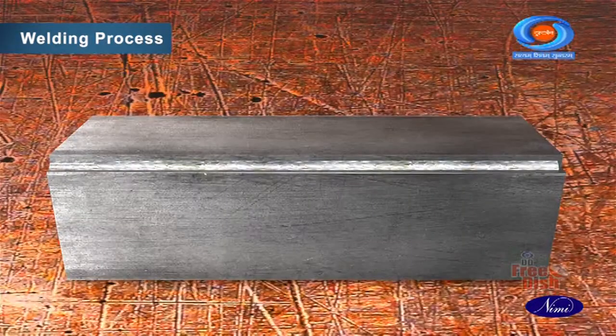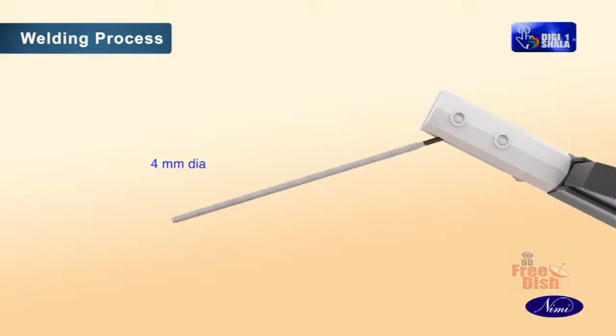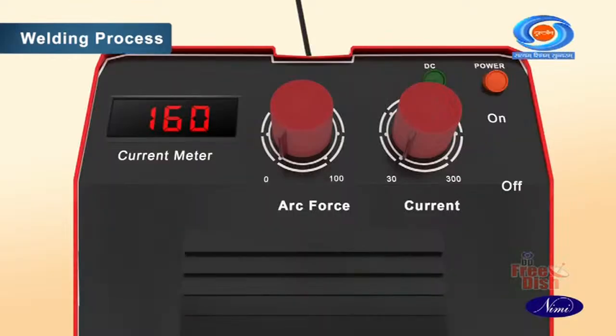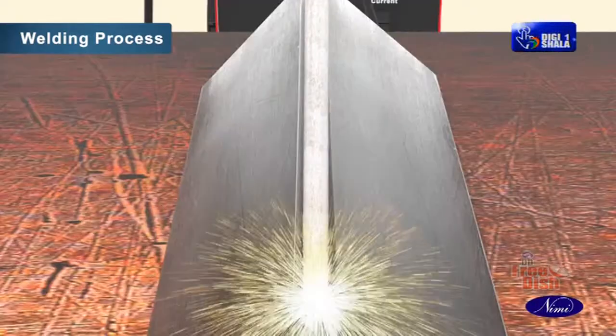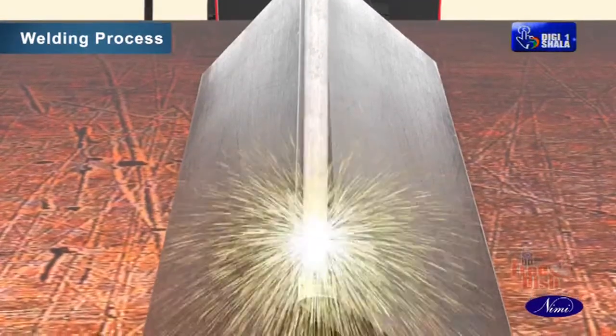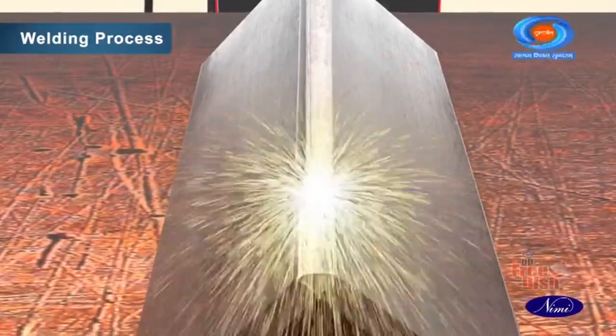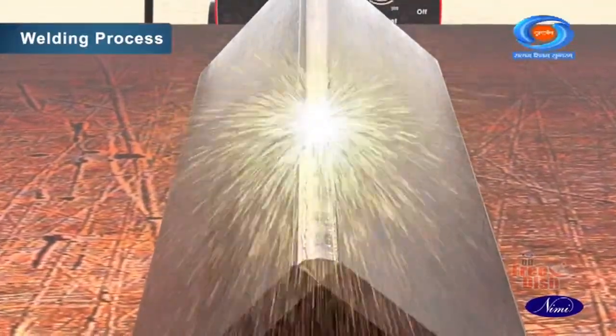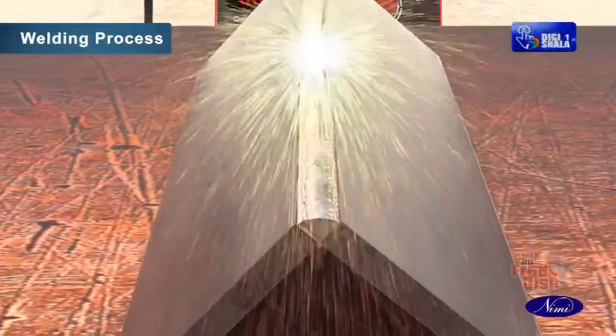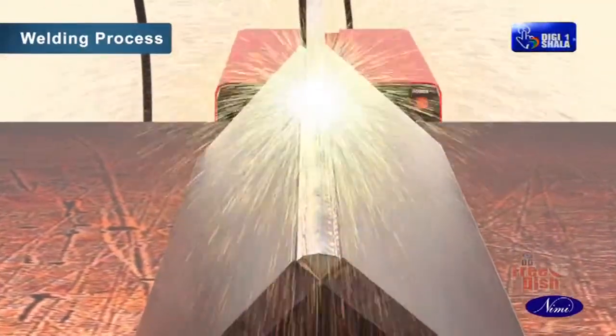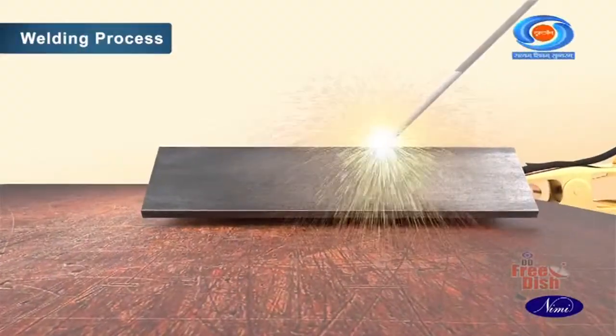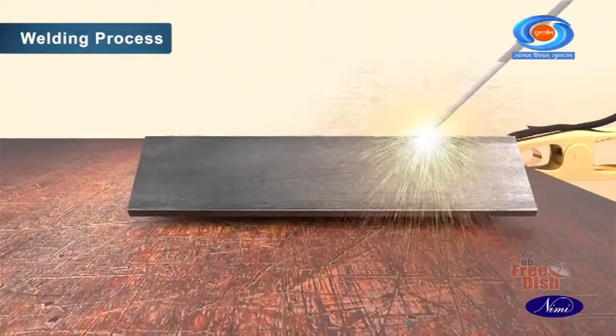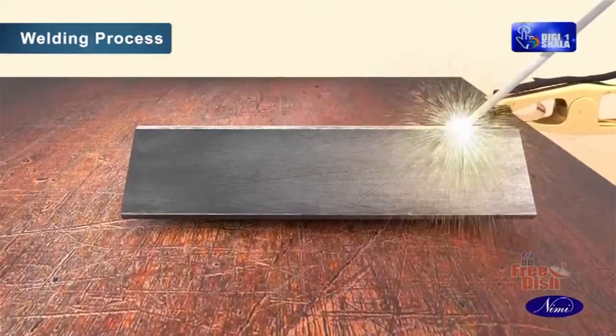Deposit first covering layer, that is the second run, using 4 mm dia medium coated MS electrode and with 160 amps welding current. A weaving motion of the electrode has to be given to ensure enough metal is deposited in the groove and both edges of the plates are fused. Ensure that the electrode angles are uniform with medium arc length. Uniform normal travel speed should be maintained.